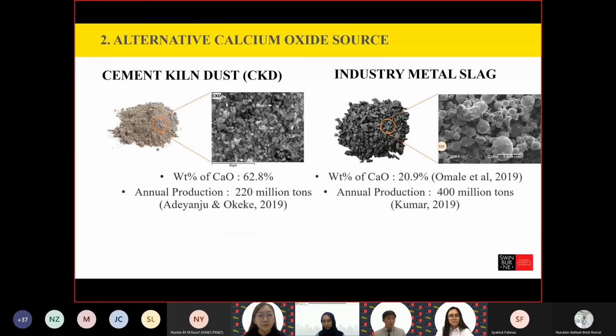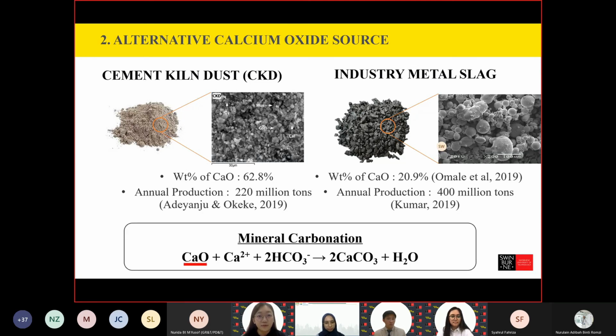The second approach is to replace lime with an alternative calcium oxide source from industrial waste. Cement kiln dust, a byproduct from cement manufacturing, was used in this project because of its high CaO content at 62.8% by weight, compared to industrial metal slag, which contains 20.9% of CaO by weight. Both sources produce 220 to 400 million tons annually. Calcium oxide reacts with the bicarbonate solution in metal carbonation to produce calcium carbonate that binds the sand to produce lime mortar. This ensures stable sequestration of CO2 in the construction material.